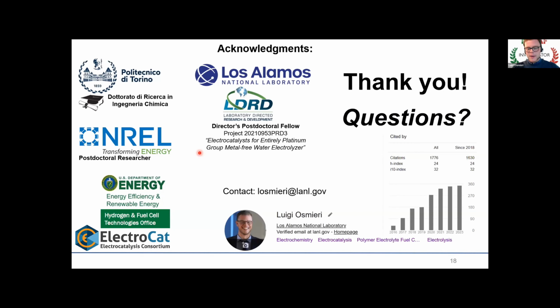Talking about the other part, the oxygen reduction reaction catalyst for fuel cells, I think the biggest contribution that I gave is trying to understand why these electrodes perform in this way when we change the fabrication method and the ink formulation parameters. This has been done a lot for standard platinum catalysts in the past, but there was almost nothing done for PGM-free catalysts. I think I published 5 papers in this area, and hopefully I helped other people working in this area to understand something more and build their research on my preliminary works, let's say.